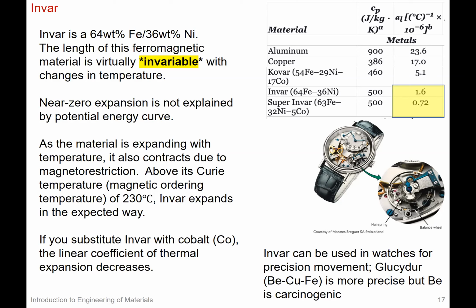So that means the spins within this material, for iron, are correlated, and thus the magnetism is actually constricting the expansion. So they're dueling forces. And so while you experience expansion as a function of temperature, there's an opposing contracting force. And so it makes this material invariable in terms of its size as a function of temperature. And so that's been used in watches for precision movement, but more recently it's been replaced by this beryllium, copper, iron compound, of course an alloy, for higher precision.